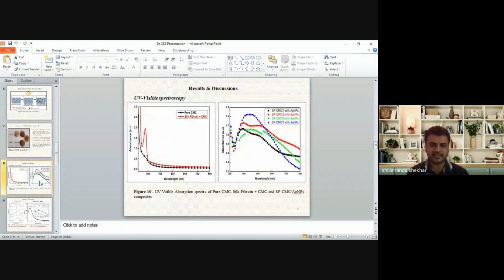Then come to the results and discussion. We have done UV-visible spectroscopy. Here we have plotted the pure CMC and silk fibroin CMC. We can observe here, for the pure silk fibroin solution, the absorbance peak is around the 270 range. We can expect the absorbance peak there. This is due to the presence of amino acid residues present in the silk fibroin.